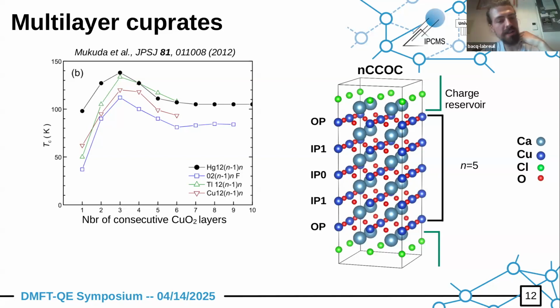Yeah, at least here, the trend of Tc versus number of copper-oxygen layers does not seem to be necessarily linked with the interlayer coupling; rather, when you have two layers, they are slightly less correlated. So I don't think that the interlayer coupling would necessarily be the main ingredient. Here it's rather that these planes are doped very inhomogeneously, and this is what probably shapes the superconducting properties of these systems in the first place. Okay, got it. Thank you very much for answering the question. Yeah.